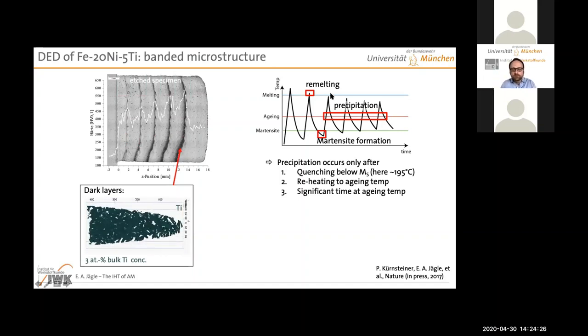Look at this schematic here on the right. This is basically a cartoon of what is happening in this maraging steel during intrinsic heat treatment. First, you deposit the layer, you melt the material, then you quench it all the way down to martensite. Then maybe you remelt it once because your melt pool is always a little bit deeper than a single layer. And then you quench it again and you have martensite formation. And then you go up again with this peak-like reheating and you cycle somewhere in the region of the aging temperature, and that should give you precipitation.